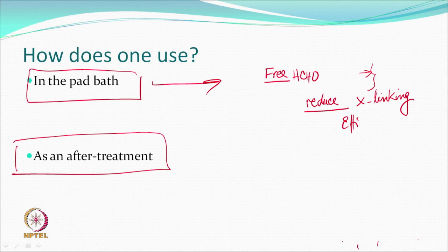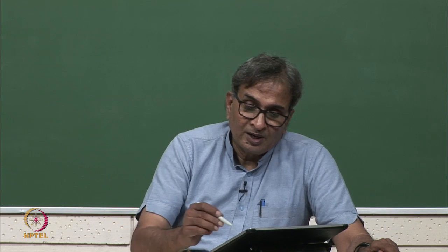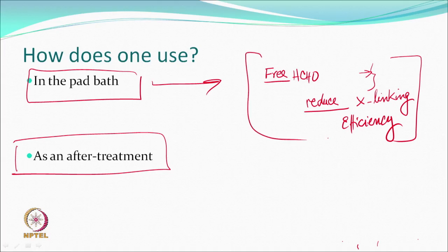All right. So, what it means? You are compromising on the effectiveness of the cross linking itself, because something which could cross link with the cellulose, the hydroxyl group of cellulose, now has been bound by some other agent, which is going to happen because both of them are present together. So, this one becomes a limitation. Usefulness is there, but there is a limitation. As far as the formaldehyde release is concerned, you may be able to control it, but you may have to agree that there is going to be less cross linking, and therefore, crease recovery angles can drop, although formaldehyde release would be reduced.